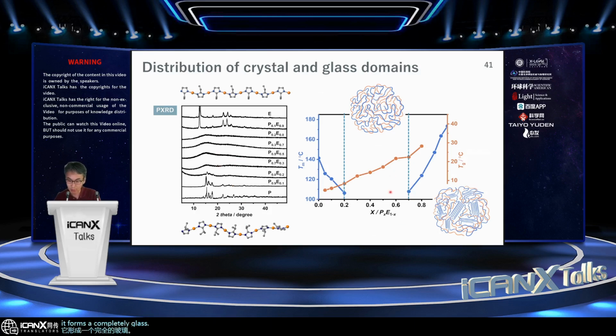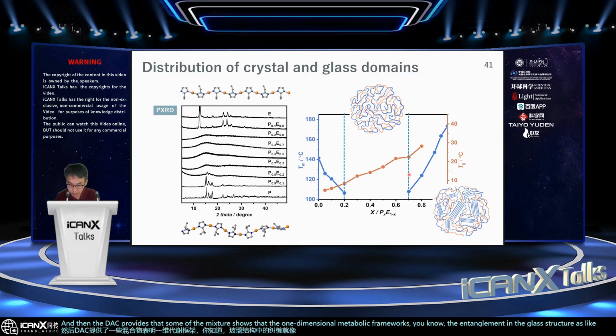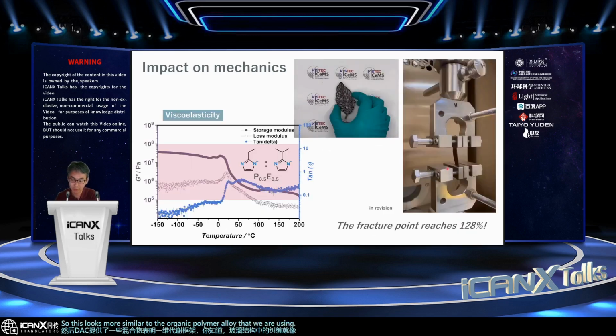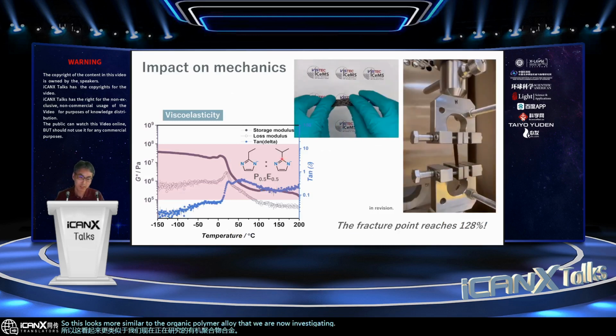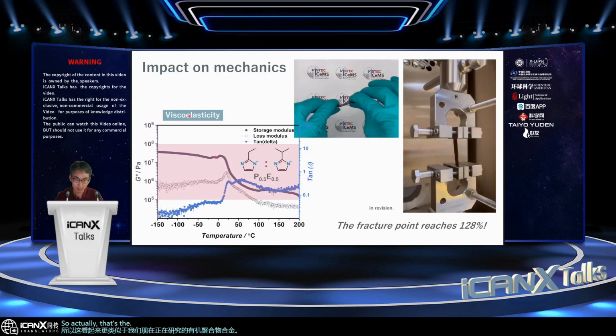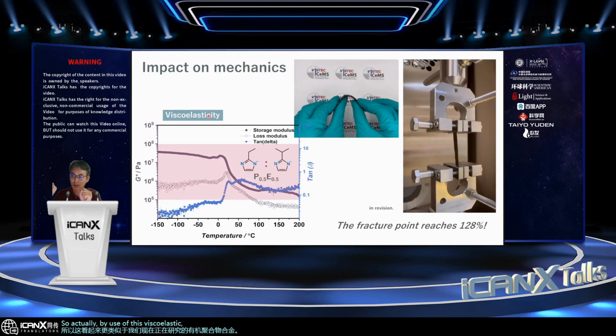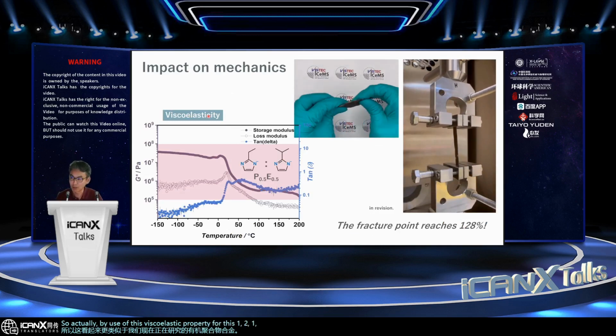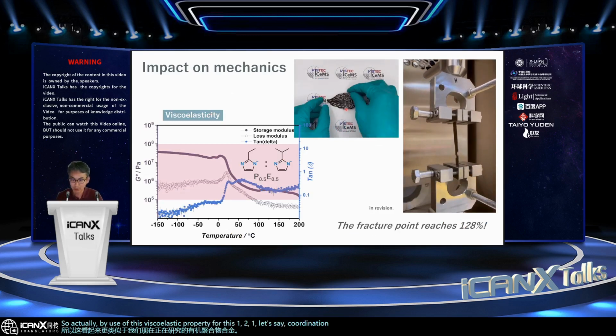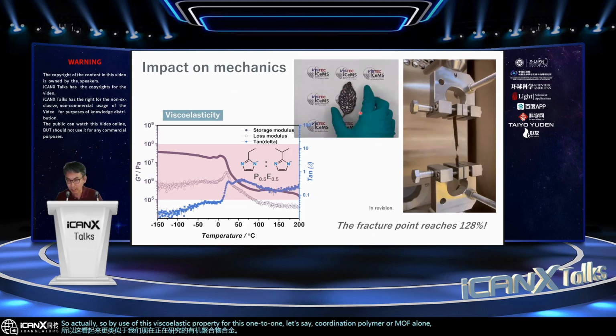And then the DSC shows that the mixture has one-dimensional metal organic frameworks, with entanglement in the glass structure like this. So this looks more similar to the organic polymer alloy that we are now investigating. So by use of the viscoelastic property for this 1-to-1, let's say coordination polymer or MOF alloy, and this is without any filler, okay?